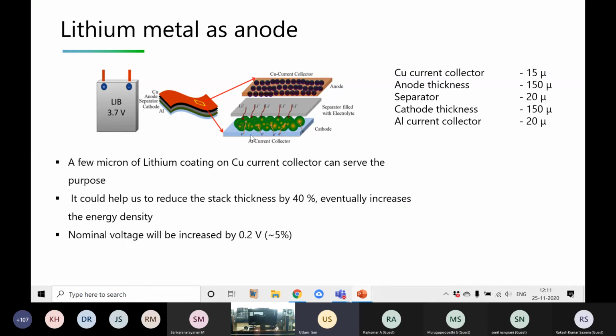Now, if we use a lithium coating instead of this graphite anode, from 150 micron we can reduce to a few microns, like 1, 2, or 5 micron. So we can eventually reduce the thickness by 40%. Okay, so that we can increase the energy density tremendously. Around 40% energy density can be increased, and the nominal voltage is also increased by 0.2 volt, which is again around 5%. So you can see around 50% we can jump if we move from present day lithium ion cells, or we can just replace graphite with lithium.